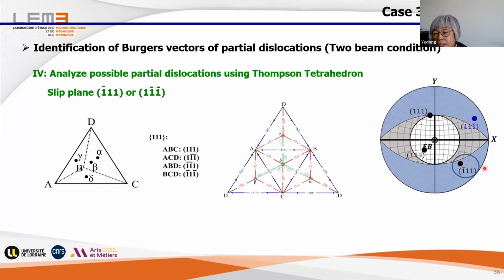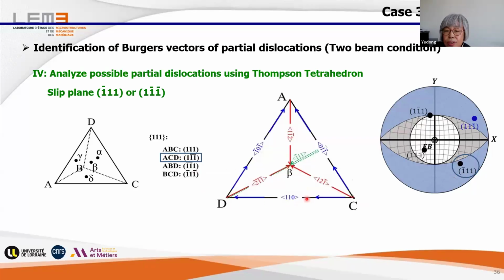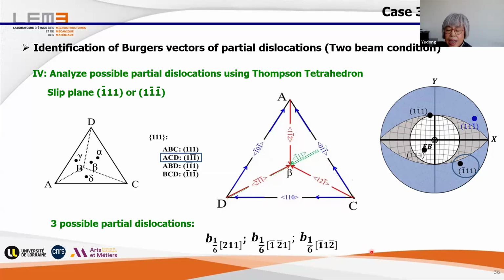And with the indices of this plane, we see this phase. And then if we enlarge it, it is here. And we know we have only partial dislocations. And so on this plane, we have only 3 partial dislocations as candidates. And so the Burgers vector of the partial dislocation is one of these three. So the scope continues to decrease.